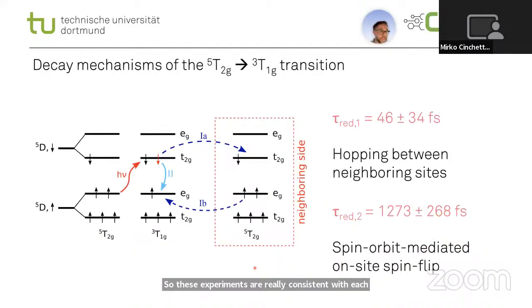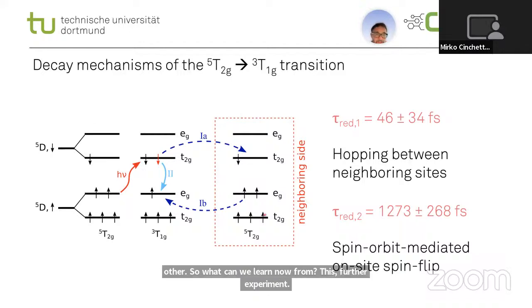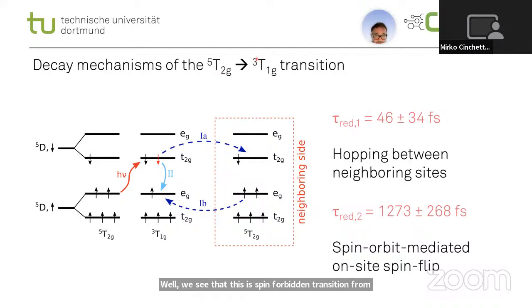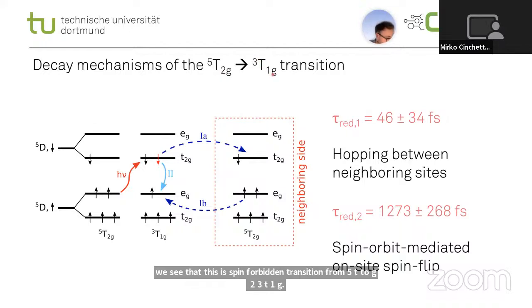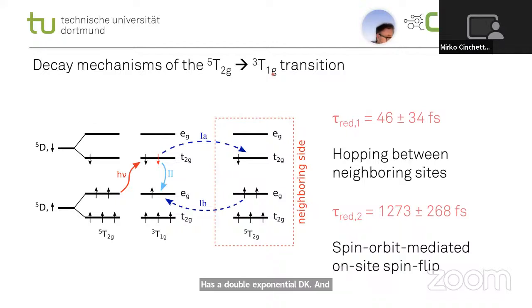And then at lower energies, at the same energy as in the previous experiments, we also see the fingerprint of the first spin conserving DD transition with the same time scale that we observed before. So these experiments are really consistent with each other. So what can we learn from this further experiment? Well, we see that this spin forbidden transition from 5T2G to 3T1G has a double exponential decay. And this indicates the presence of 2 independent decay channels in the relaxation of this transition back to the ground state. Basically, these 2 pathways have a decay constant of 50 femtoseconds and 1200 femtoseconds.